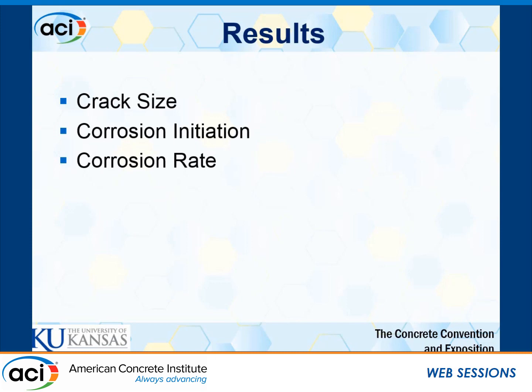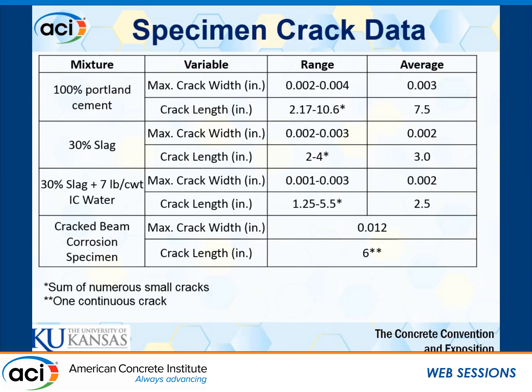So getting into results now, we'll quantify some of our settlement cracking results here, and then get into our corrosion initiation times along with our average corrosion rates based on loss at a fixed time interval. So for settlement cracking, what we've seen in general at KU, our little 10-cent explanation, is when we use a crack reduction or shrinkage reduction technology, we're also seeing reductions in settlement cracking.